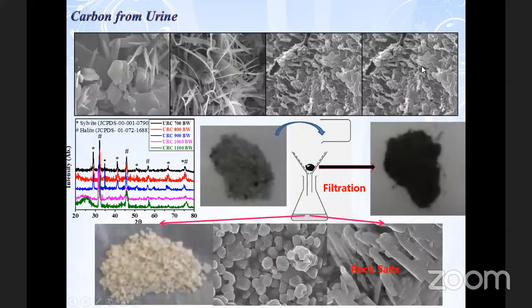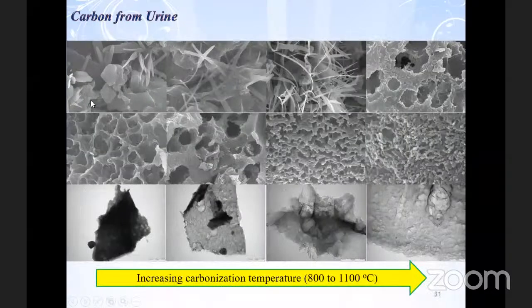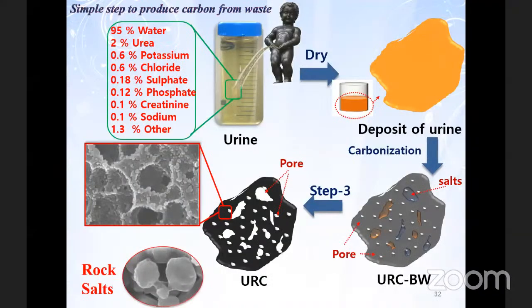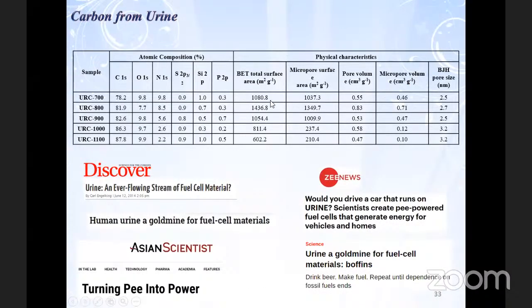So when we carbonize it and simply wash it using acid, we got the carbon material. Okay, and that carbon was a highly porous material. You can see many different pore-like structures from these TEM images compared to the one we synthesized without washing. And we studied in detail the different carbonization temperature effects and the washing effect. If you go to the physical characteristics, the surface area was 1,436. Very high surface area was achieved with a very constant pore size. And we had various detailed studies on the different.